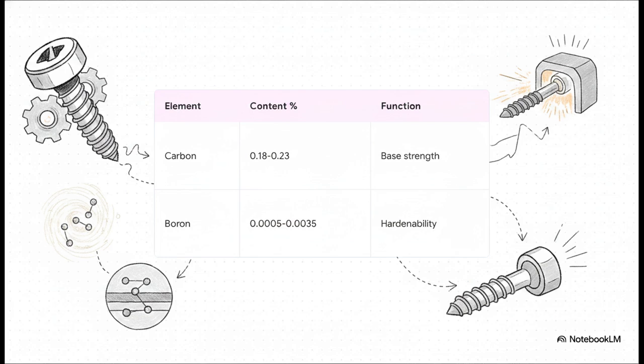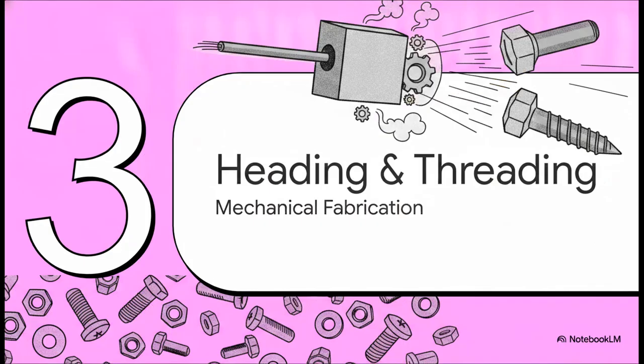But that tiny fraction of boron is an absolute game changer. It blocks the formation of soft ferrite inside the metal, which guarantees the steel will harden completely through its core when we heat treat it later. And it does this while letting us keep the overall carbon content low, meaning the steel stays soft and bendable right now, which is exactly what we need for the next step. Okay, part 3, cold heading and threading.